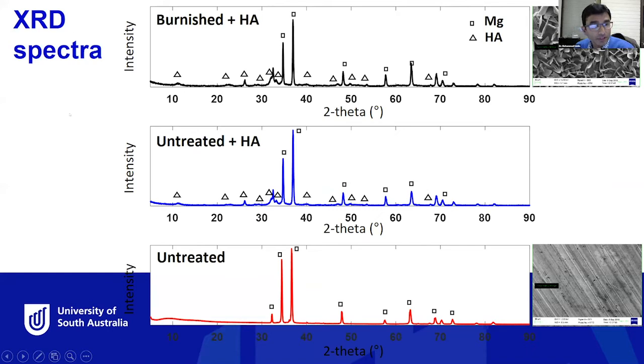Furthermore, we have done some further XRD analysis to investigate the crystal phase, I mean the compound formation of the HA. So we can see that this is the untreated surface where we can see mostly the magnesium. But when you deposit the HA coating on top of the burnished surface, we can see the presence of the HA compound.